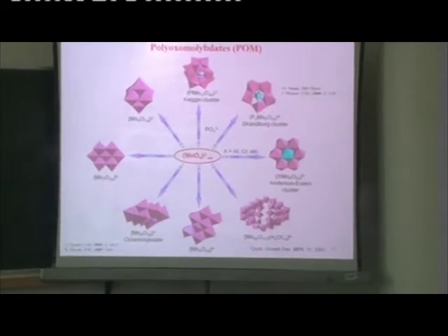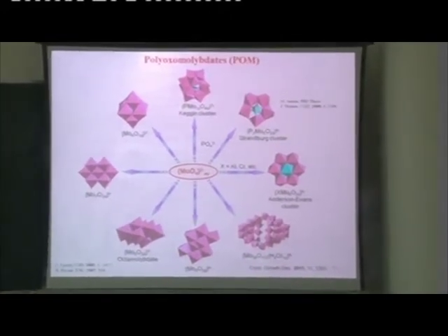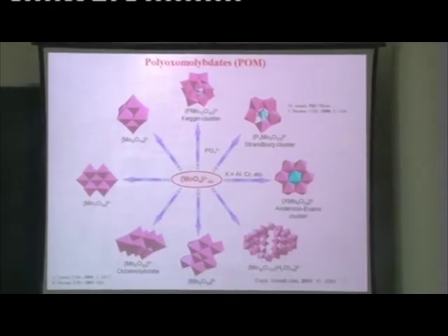Now, which one works? Many a time you only tell from the experimental data. Now, you take heptamolybdate solid, you put it in water, there is no guarantee the solution contains only heptamolybdates. There is a good possibility that you may have other species coming up. Now, what actually crystallizes again depends on the other species present in that. Right? You have to work it out in a particular system, because of your phase diagram, because many a time these are all kinetically controlled phases, they need not be equilibrium phases. Keep that also in mind.